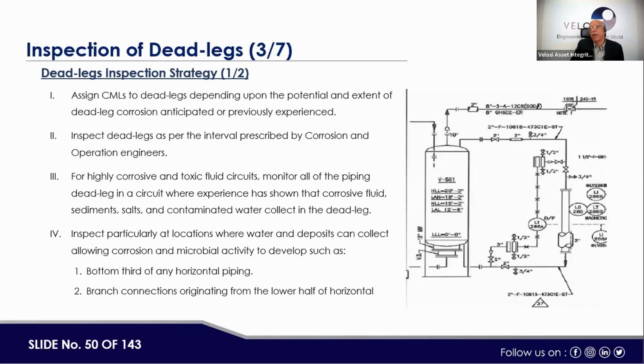Inspection strategy. For example, how a dead leg inspection strategy should be developed. What we are used to doing, for example, if there are small bore connections like vents or drains on the piping systems, is we can call for profile radiography in one go, and do condition assessment of those piping systems as one campaign. Similarly, mostly piping can be inspected externally if it is not insulated. If it is insulated, then the possibility of removing insulation depends upon the operating temperature of that particular segment. If we cannot touch the pipe because it's too hot, then we have to inspect during the shutdown, or we can inspect the piping system during normal operation as an online OSI program, an on-stream inspection program.